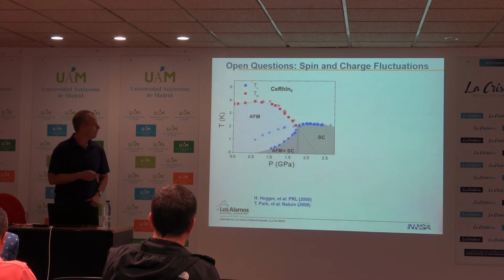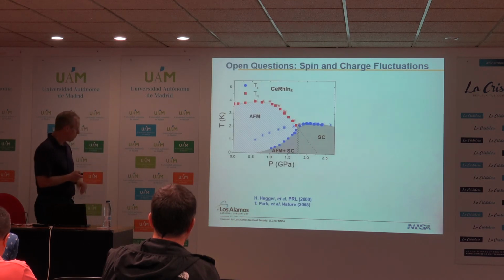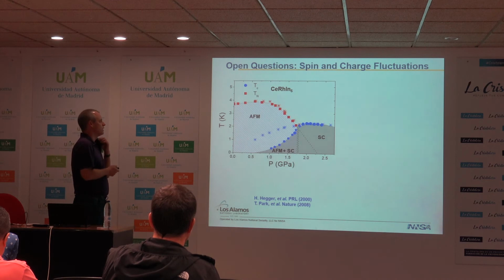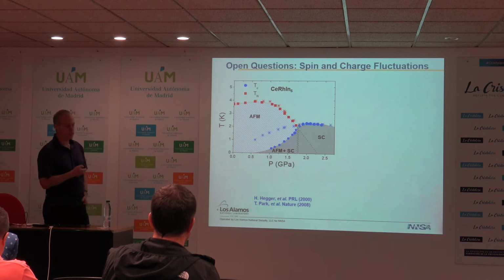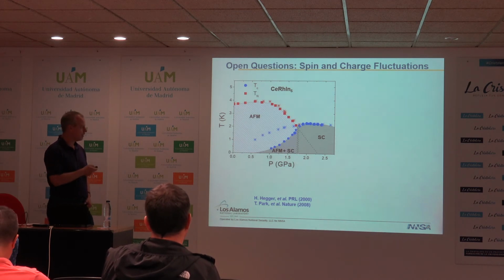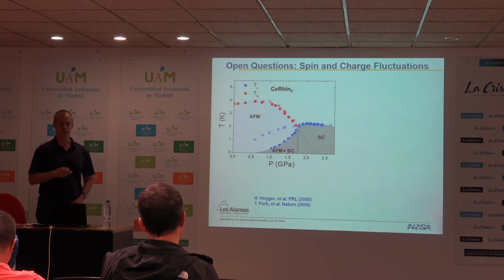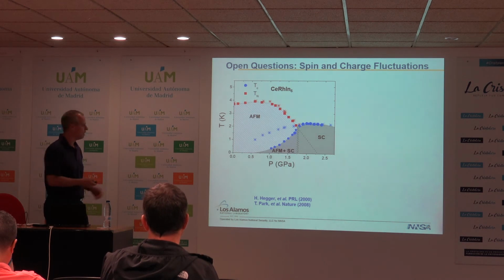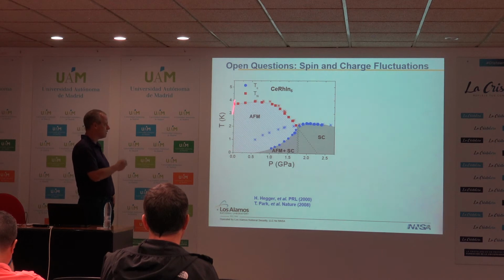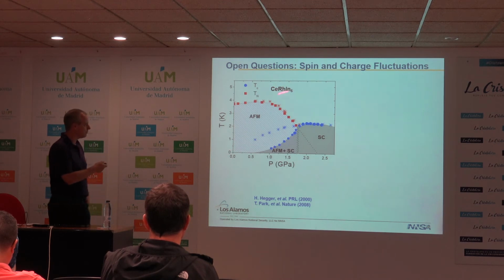Okay, so one of the additional open questions is the role of spin fluctuations versus charge fluctuations. And this will maybe at first seem rather strange: why am I mentioning charge fluctuations? Because in cerium I really only had a system of local moments, right? So here again it's temperature as a function of pressure. This is again cerium rhodium indium 5, magnetism, superconductivity.